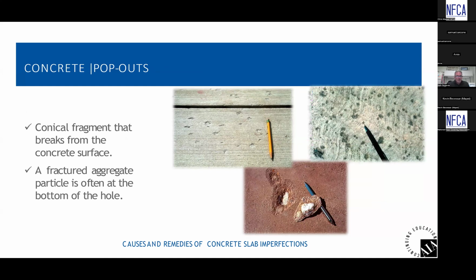Pop outs, you can see these on occasion, both interior and exterior. In some cases, it's an aggregate material that somehow slipped in that's not supposed to be in there. I'm in Western Pennsylvania, and we're a heavy coal area, and sometimes bits of coal get in with aggregate, and it's not supposed to be in there. So when the aggregate gets placed into the concrete, we have bits of coal, and sometimes we'll see these types of pop outs, and you see a little bit of coal right at the base of the conical pop out. There are other materials that sometimes slip in that shouldn't be in there that can cause pop outs.